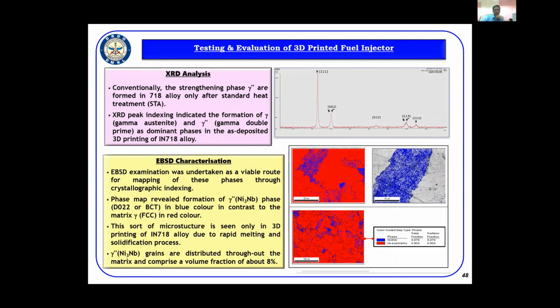A little XRD analysis has also been carried out to understand the strengthening phases. As we are all aware, in the 718 alloy, gamma prime and gamma double prime are the strengthening phases that are obtained only after heat treatment. But we could get these strengthening phases in the as deposited condition. The EBSD characterization phase map revealed gamma double prime in contrast to the gamma in the red color shown here, and a total volume fraction of about 8% was obtained in the as deposited condition. Again, this is due to the very fine cellular structure and the repeated melting and solidification process. That is the reason the strengthening phases were formed in the as deposited condition.